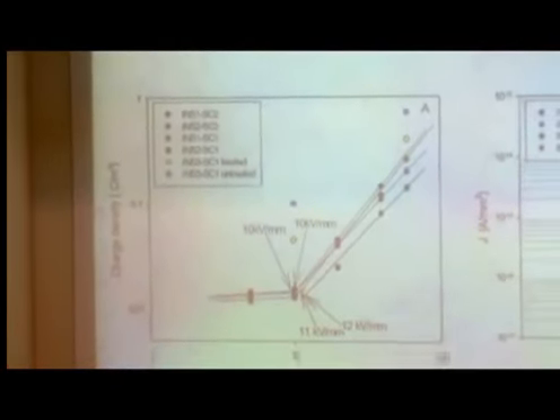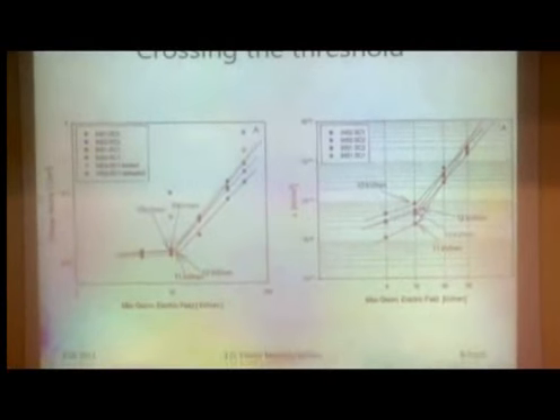Well, what do you do then? You get charge injection, extraction, trapping processes. Len told us all about that yesterday. Here you see the threshold where this happens, obtained from two different measurements. Conduction current measurements here, space charge measurements here. And you see for these materials, we have this threshold around 10, 12 kV per millimeter. It's important because in practice, we will always use fields above this value. So we have to deal with space charge trapping.